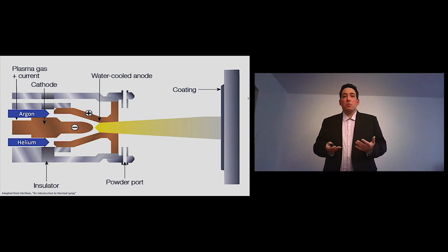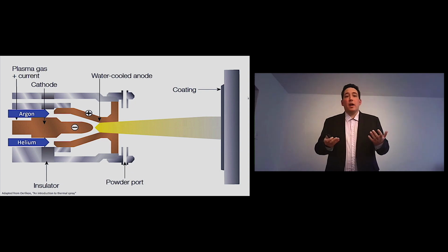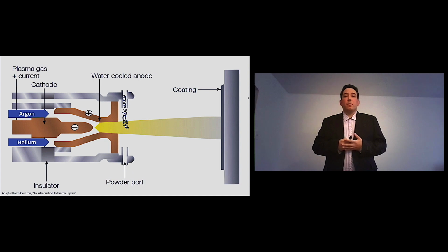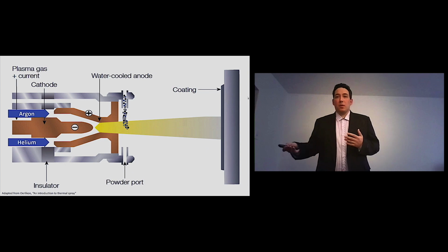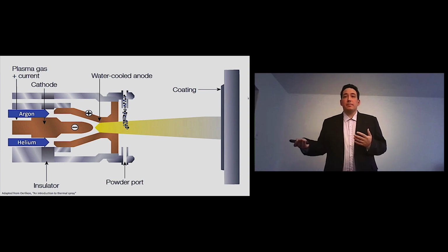Gas flows from left to right, either argon or helium or other inert gases. And as they flow and approach the tip of the gun, we apply a huge voltage there. This voltage can dissociate and ionize the gases and make plasma, just like Helena just told you. This ionized gas and plasma is really hot and can melt all the particles that we put in. These melted particles are accelerated towards the coating or the surface that we want to protect, building up the coating.